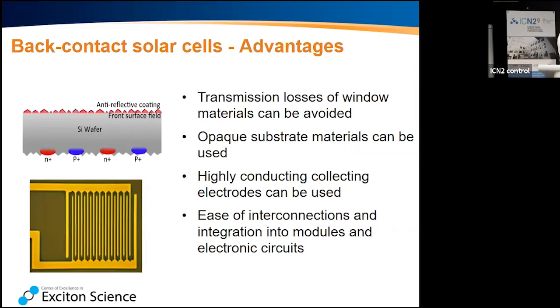Back contact solar cells, and I give you an image here of a silicon back contact solar cell. Instead of having the contacts on top and below of your absorber material, you're hiding both of the contacts underneath your solar cell. That frees up the space on top of the solar cell to optically couple the light into it. So that's one of the main benefits. You avoid transmission losses of window materials, and you can also use an opaque substrate when we talk about thin film solar cells. Your conducting electrodes don't need to be transparent or have any optical requirements. They can be metals, for example, anything you want. And it's also easy to interconnect them once they sit on the same substrate.